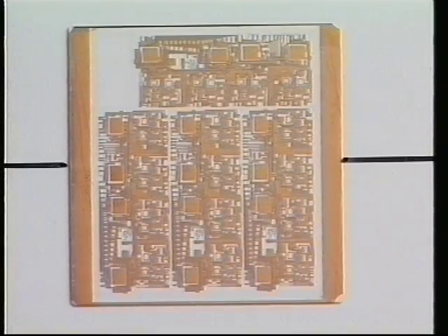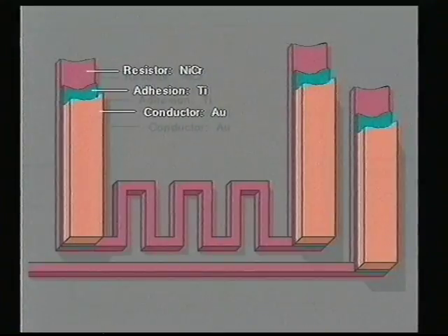Like in thick film hybrid technology, resistors can also be made as part of the substrate, but the layers are thinner, normally less than 2 micrometers. In standard thin film hybrid technology, the substrate has an upper layer of conductors and a lower layer of resistors. The lower level is made of nickel chromium, which gives a relatively low conductivity. The upper layer of conductors is made out of gold, giving very good conductivity. To improve the adhesion for the gold layer, a very thin layer of titanium is deposited between the nickel chromium and the gold.